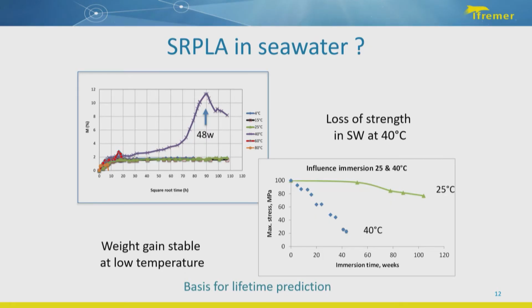When we saw that at low temperature the material was really stable, here on the weight gain graph we are up to a 1 year test, we did some mechanical testing. It's the second graph on the bottom. It was a tensile test, performed on samples immersed at 40 degrees and 25 degrees. You can see here the maximal stress as a function of the immersion time in weeks.